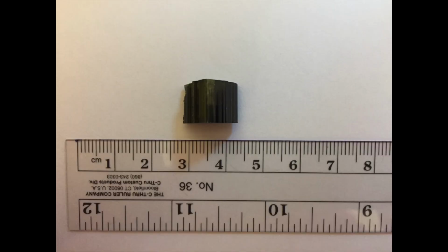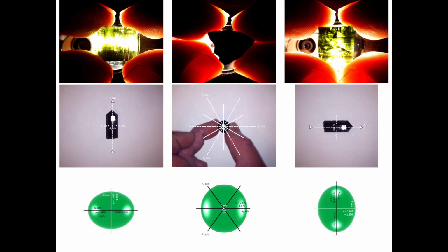Also note that in tourmaline, refractive index omega being associated with near complete absorption of light is only true for certain colors of tourmaline. My goal for our tourmaline slice, however, was to produce a mineral sample that could exhibit pleochroism under normal lighting conditions, so people didn't necessarily need a polariscope in order to actually show this property off. And our tourmaline slice does this job rather well. Looking down the plane of the A-axis, you'll be able to see a beautiful green color in normal light, whereas looking along the C crystallographic axis results in the complete absorption of light.